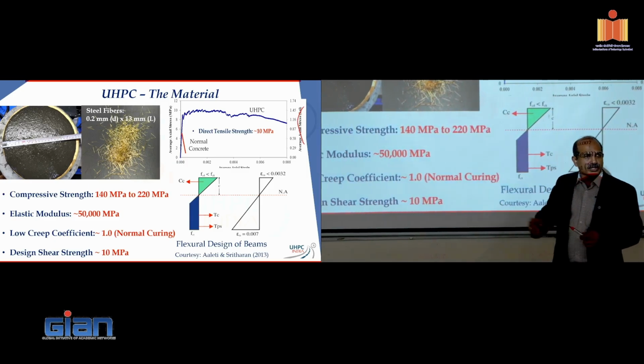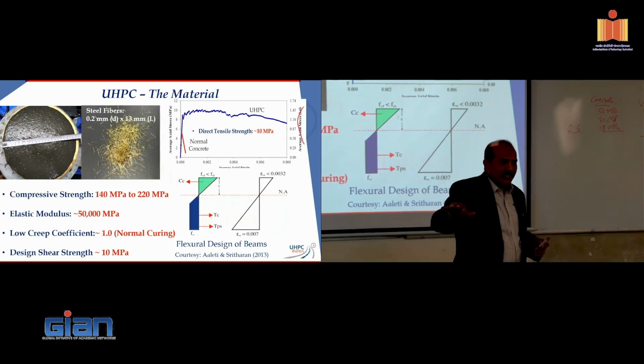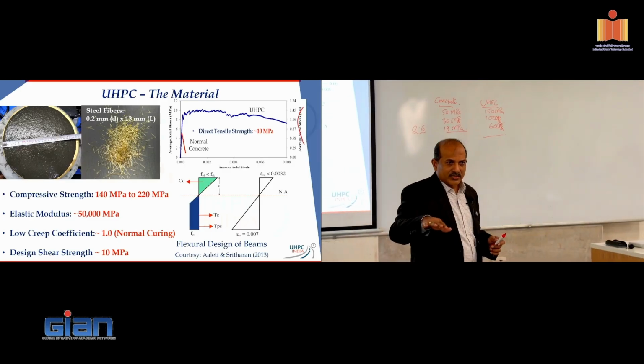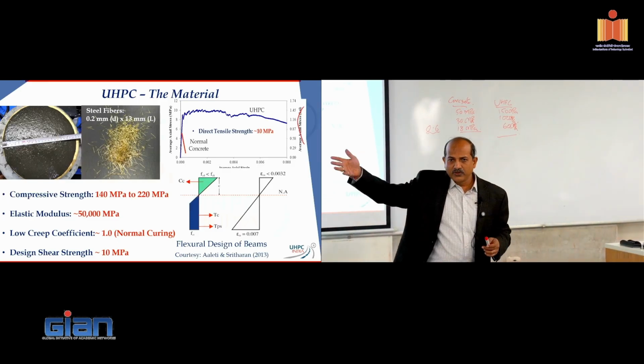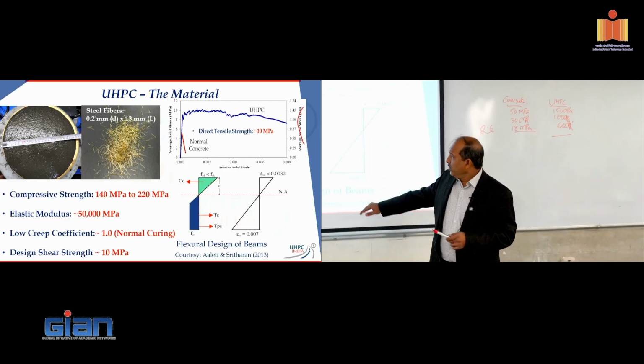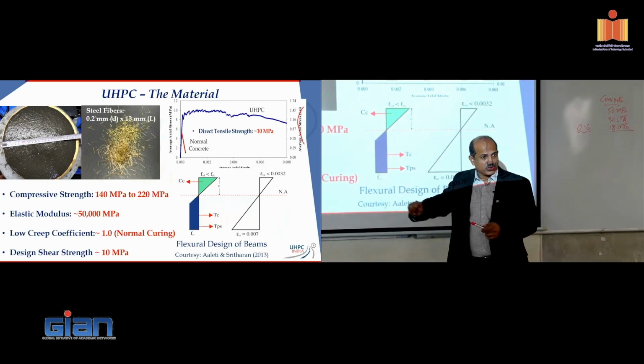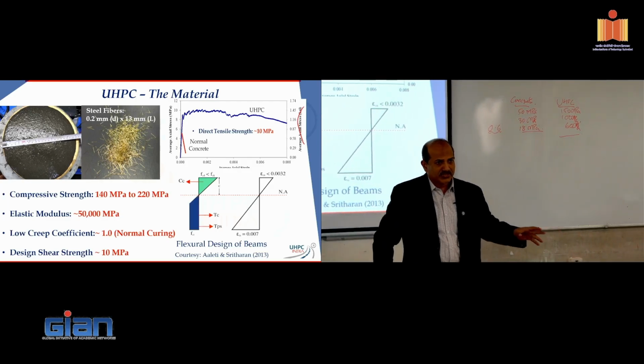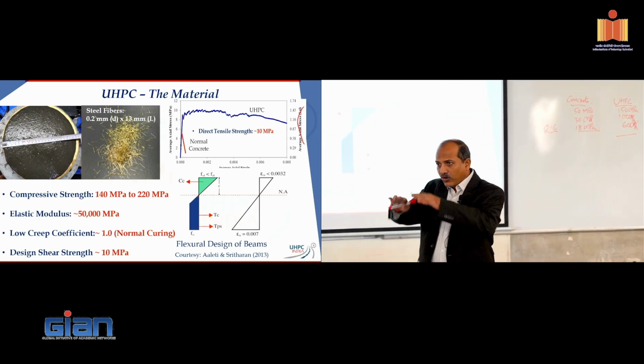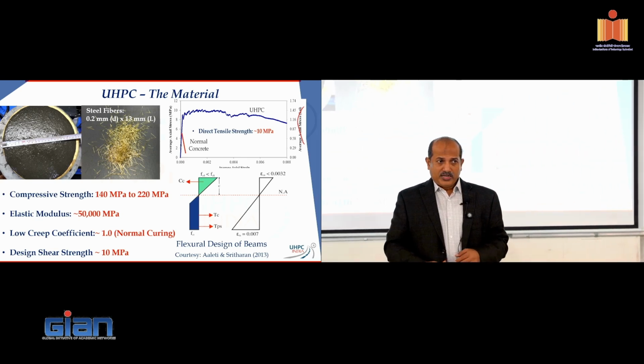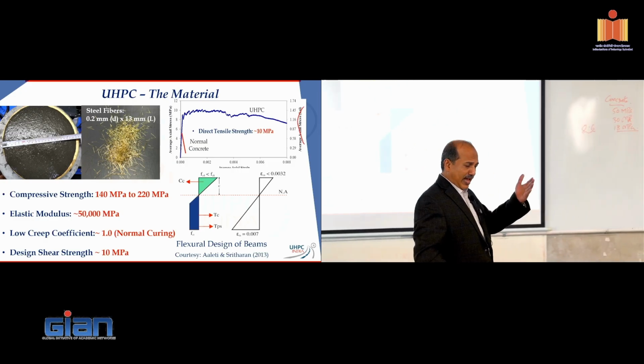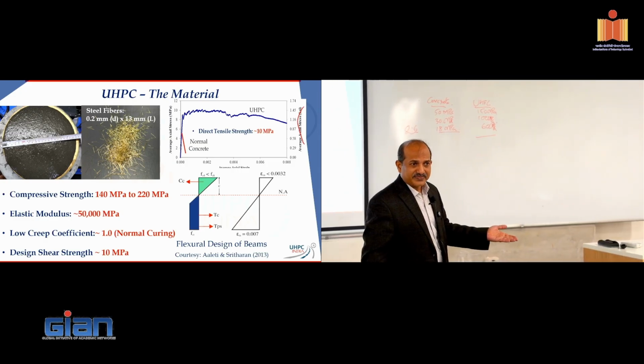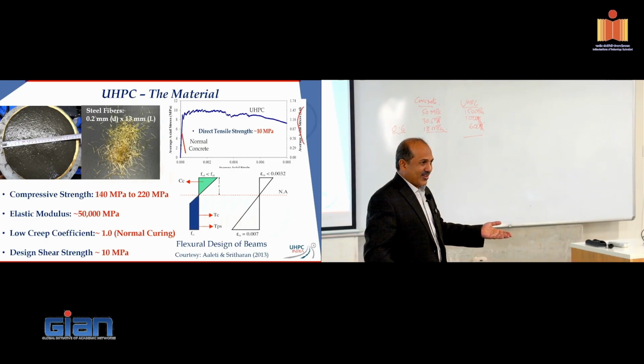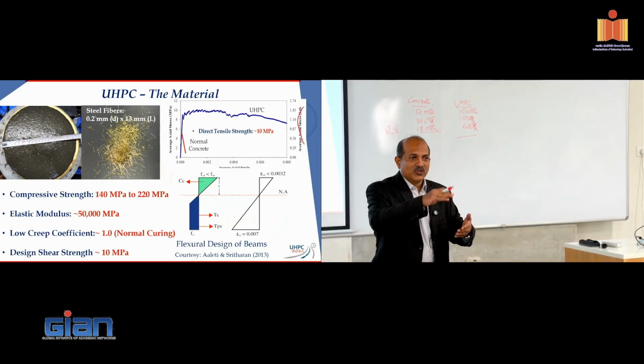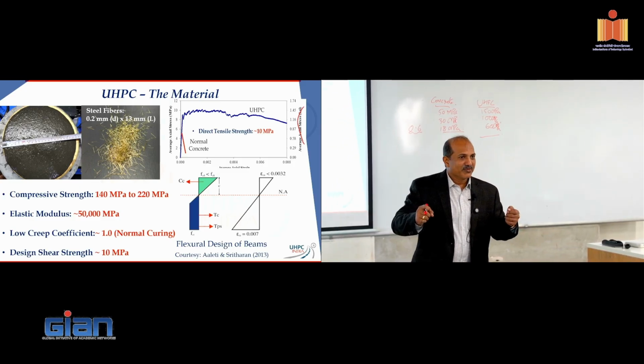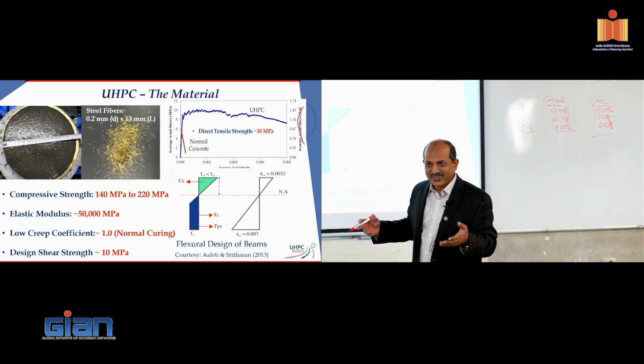So with normal curing, you're probably going to be at a coefficient of 1 or 1.1 as compared to 2 or 2.2, which is there for concrete. If you go ahead and steam cure your UHPC for 48 hours at 90 degrees Celsius, it is possible to reach numbers as low as 0.2, 0.3. Okay, which is you're getting to almost nothing, and it's pretty much acting like structural steel out there, right?